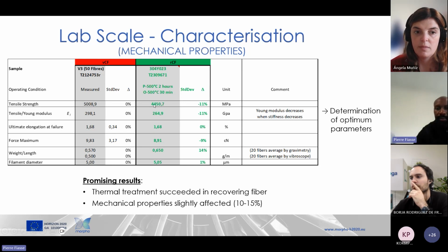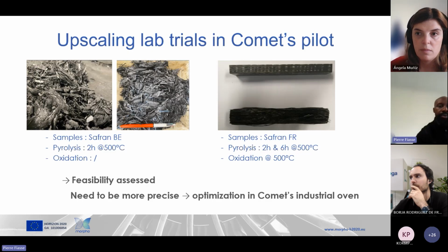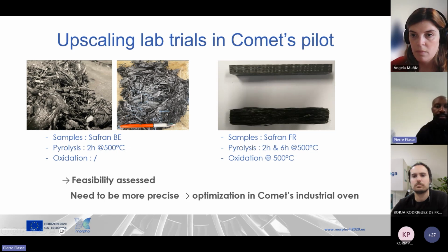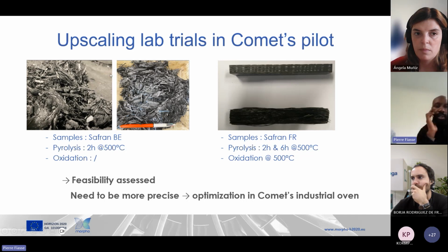Yes, that's it for the slide. When we finished with the lab scale tests, we decided to transfer all the tests to the pilot, and we started with a test with the Safran Belgium sample, and we got this recovered fiber. What we can see on this recovered fiber is that the pyrolysis was good, but all the fiber was interlocked. So it was more difficult afterwards to get data on this fiber, and we decided to continue tests on the static reactor to avoid the interlocked fiber.